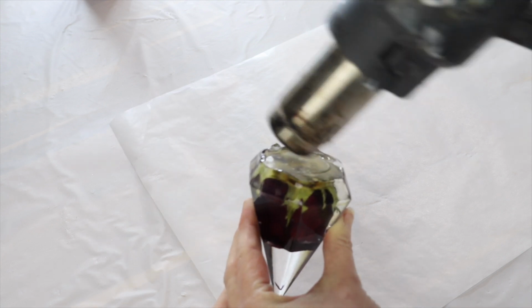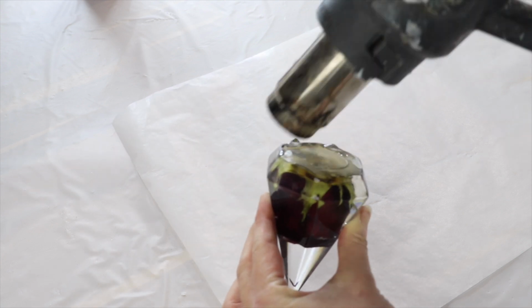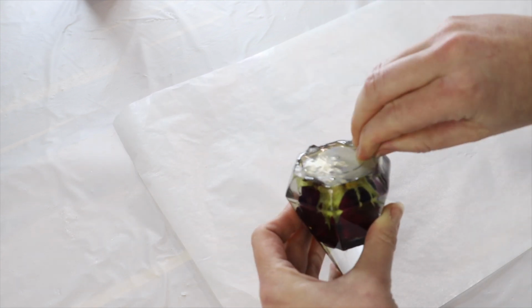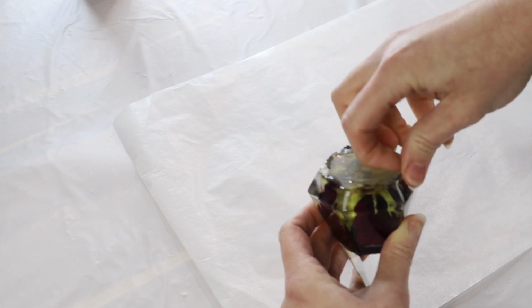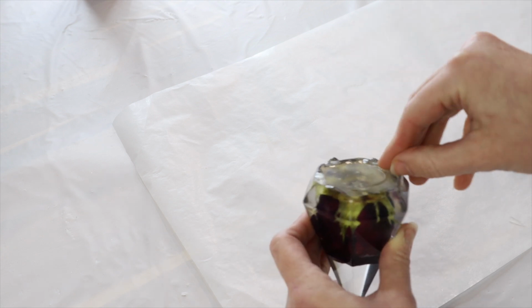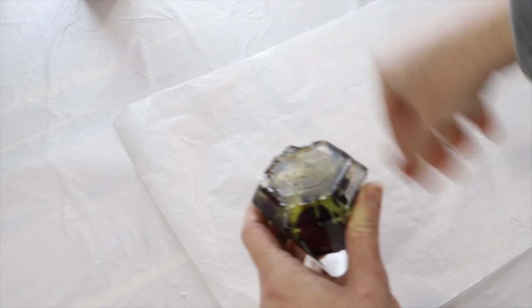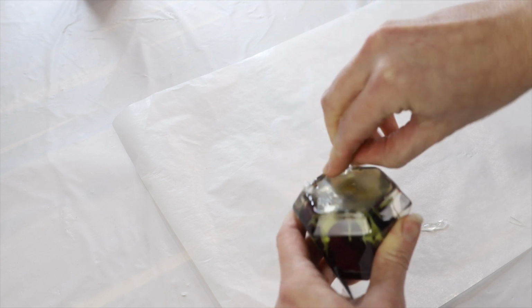had the PVA glue. But if you do ever get some resin that's a little bit hard, a few of the drips have stuck a bit better, use a heat gun to heat up that resin. That will help soften it, and then it will be a lot easier to peel away.